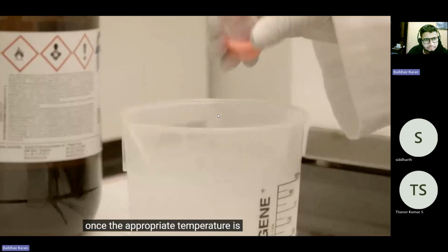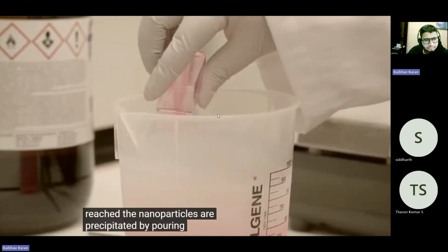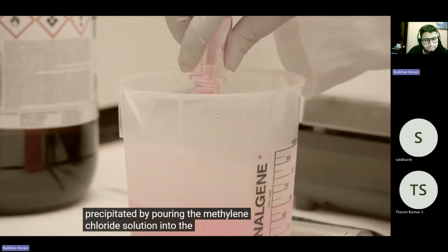Once the appropriate temperature is reached, the nanoparticles are precipitated by pouring the methylene chloride solution into the beaker of chilled pentane.